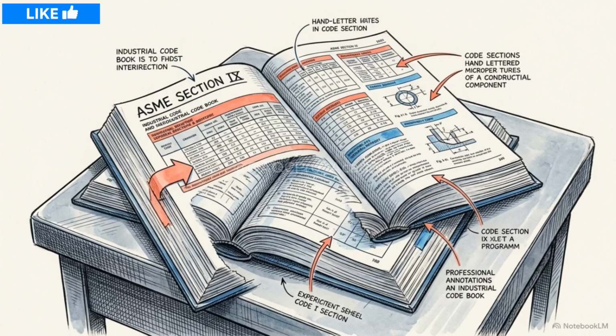Once the coupon passes, the results are documented in a procedure qualification record, the PQR. This is the permanent legal proof that the procedure works. The PQR captures the exact, actual parameters used during the test. If the welder ran the coupon at exactly 120 amps, the PQR records 120 amps rather than a target range. Once certified by the manufacturer and the authorized inspector, this record cannot be altered or revised to fit a new application. The PQR proves the metallurgy of the procedure, independent of the manual skill of the welder who performed the